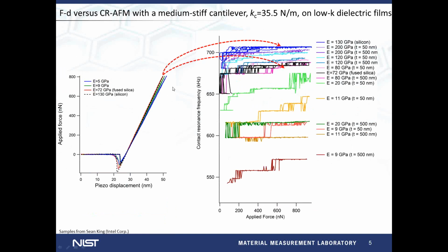And an experimental illustration is showing here of what I just explained. If we look at the force distances, we see good sensitivity. They have different slopes here for compliant materials, up to 10 gigapascal, but we don't see any difference between measurements on fused silica and silicon with this medium stiff cantilever. However, if we do contact resonance with the same cantilever on a bunch of different materials in between silicon and fused silica, we observed a bunch of other materials that we can measure, and this is in terms of sensitivity of contact stiffness, not necessarily elastic moduli. Here are different low-K dielectric materials of different thicknesses and different elastic moduli. But the idea is that we have better sensitivity in between these two stiff materials.